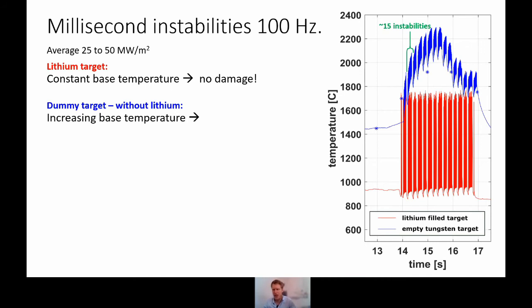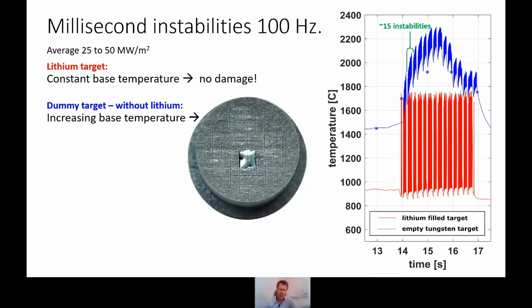Whereas the dummy target without lithium, you can see there the base temperature keeps increasing until about halfway, and then suddenly it seems to dip. And what you see there is actually melting. So there is a big melt pool of molten tungsten. The infrared emissivity of that is lower, and that is why the temperature seems to drop. And afterwards, you can see actually that we did make a beautiful drop of tungsten there on our target, which was, of course, unfortunate for the target, but it was a very interesting result.